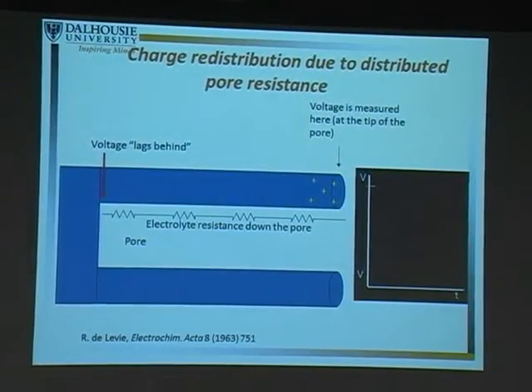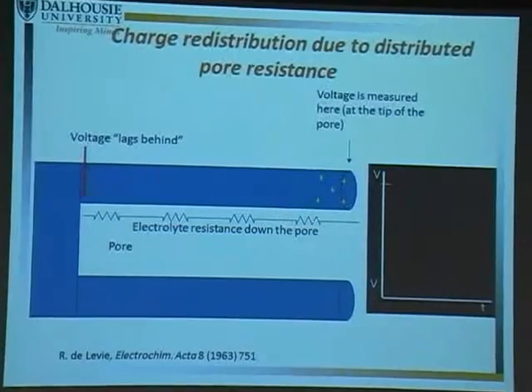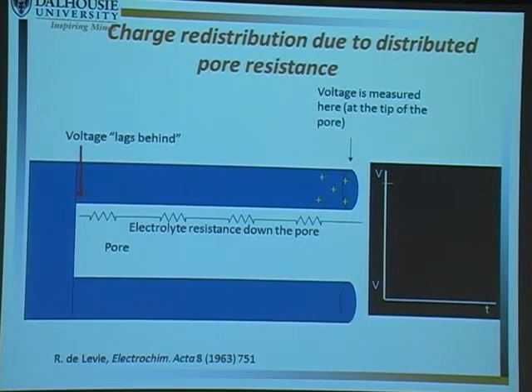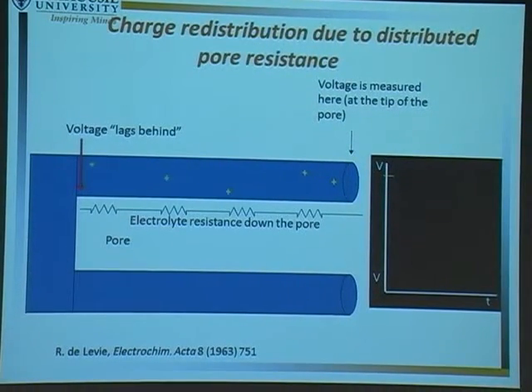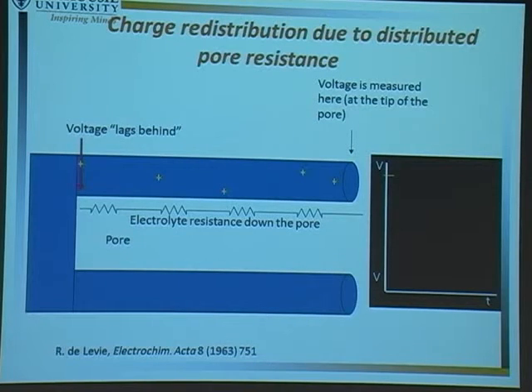So what happens is if we have more charge at the tip of the pore, we open the circuit, then that charge will equalize throughout the depth or the length of the pore, and what will happen is you would expect a drop in potential. And that drop in potential is because you're measuring the potential at the tip of the pore, but the charge has now moved down into the pore. And so it's perceived as a self-discharge, even though it's not a reaction causing this process. We haven't lost any charge.